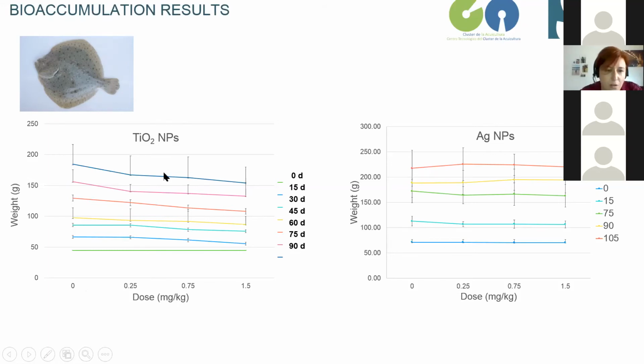It's true that with titanium dioxide nanoparticles, initially they didn't gain the weight that they should in the first times, but this was mainly due to the different acceptance of the turbot for the food, because the taste is not the same, but then they recover the appetite for the food and gain the weight as usual. For silver nanoparticles, we didn't notice even this. So we can tell that there were no mortalities, no significant different behavior, and no significant differences in weight gain during the experiments.